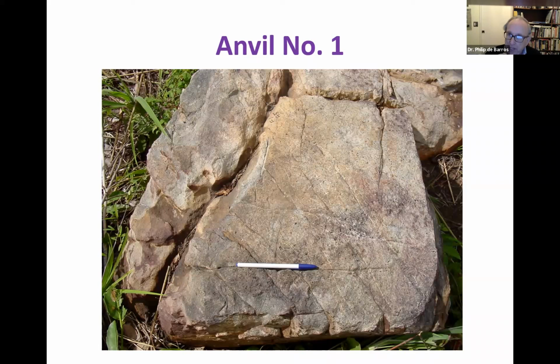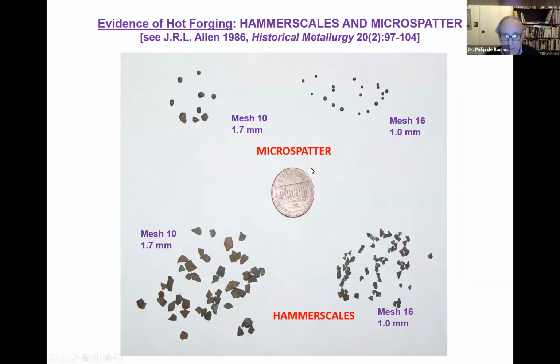Little tiny hammer scales flake off, one or two or three millimeters across, very thin, or a little micro spatter, which is liquid slag that squirts out because of the hammering. This is an example of the micro spatter and hammer scales. If you find that in the soil, you've proved that hot forging took place there.